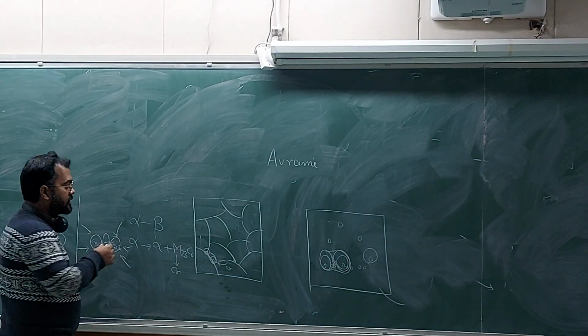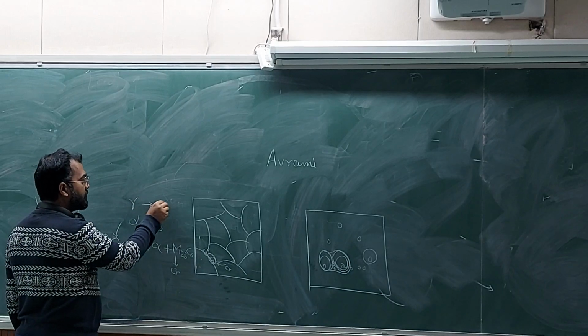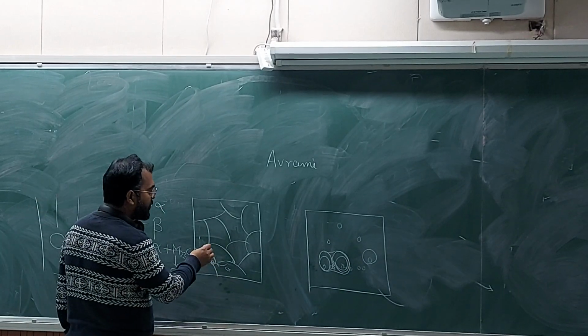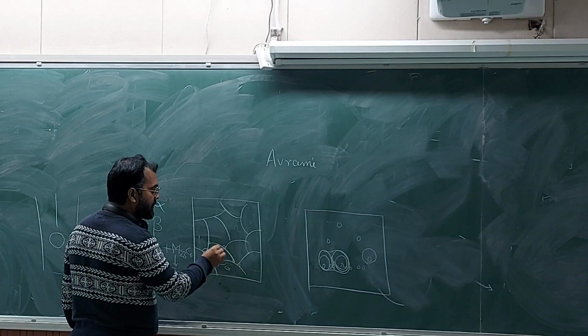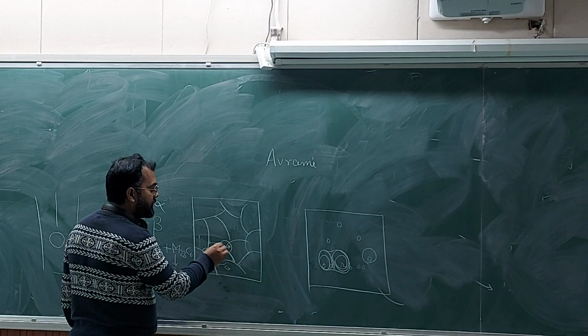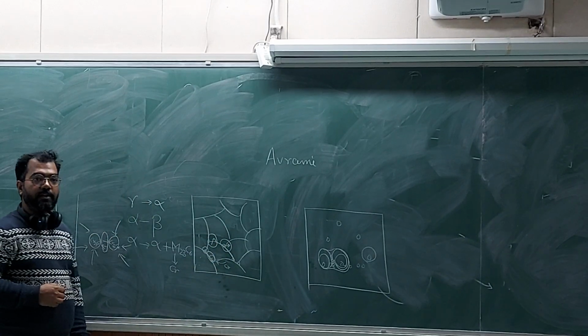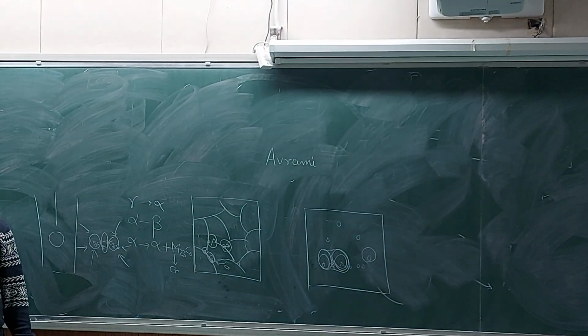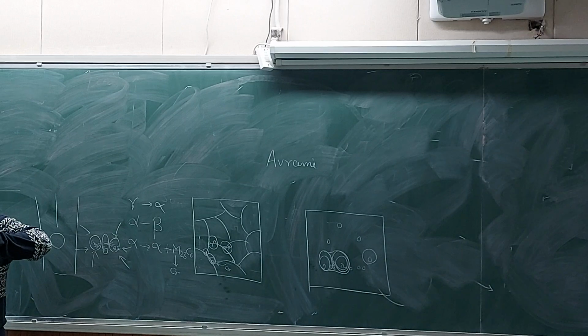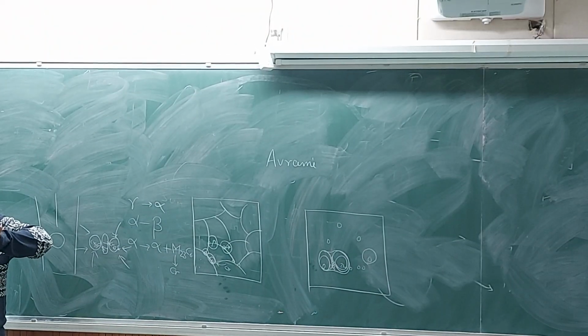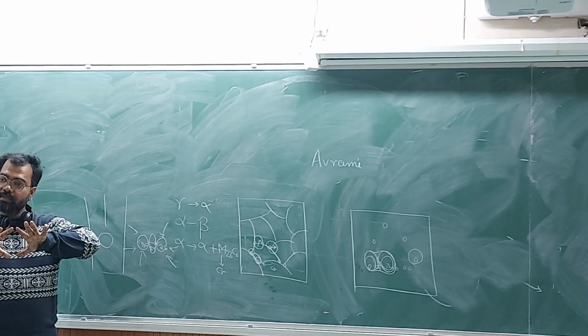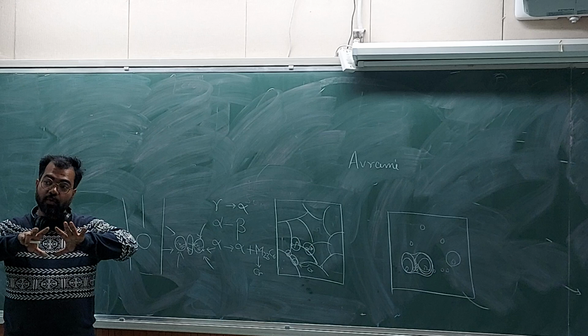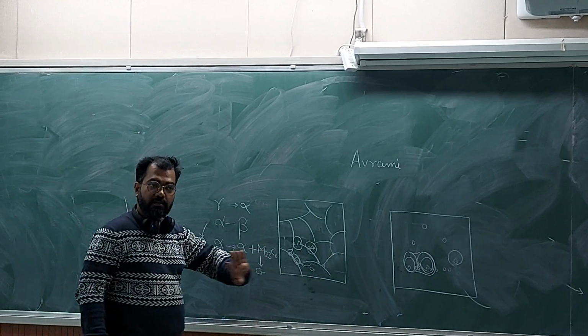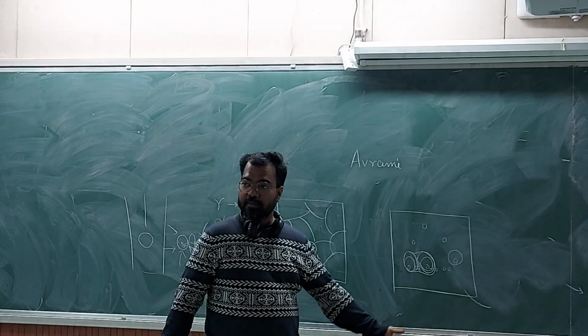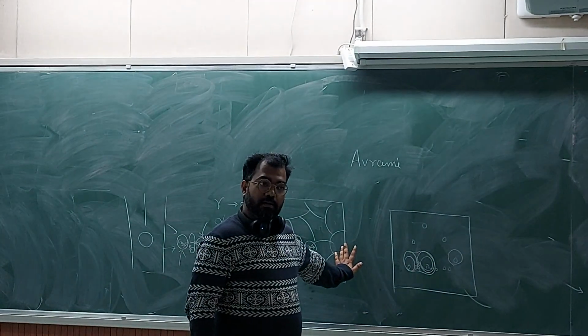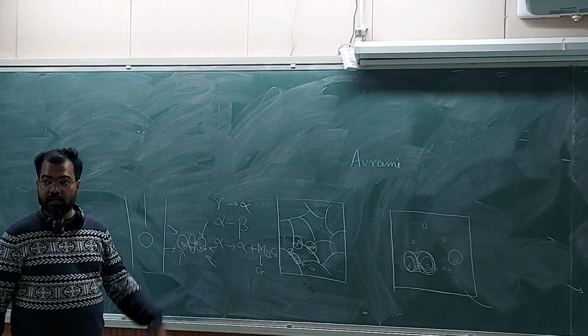Right? So suppose austenite is transforming to ferrite. So you had austenite and then you have nucleation of new ferrite phases and they are growing. Right? So each of these will have different orientation because they had no relation between each other when they were growing. So when they join, they will have a mismatch in orientation. So you will have a boundary between two transformed alpha phases, right? And that boundary will not go. But in case of void, the boundary will break and they will become one. So this is missing in the precipitation or solid to solid transformation.